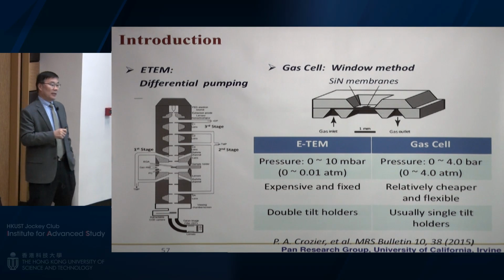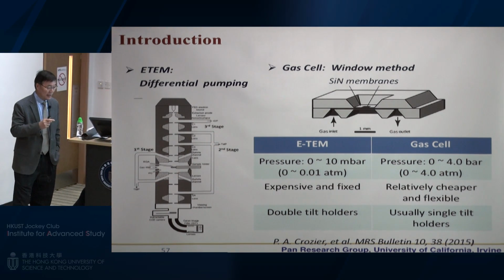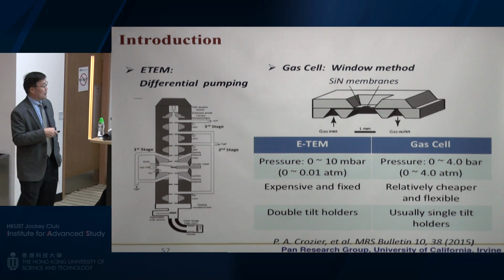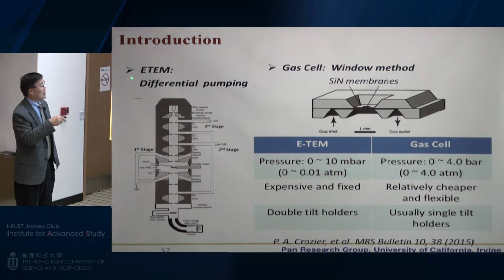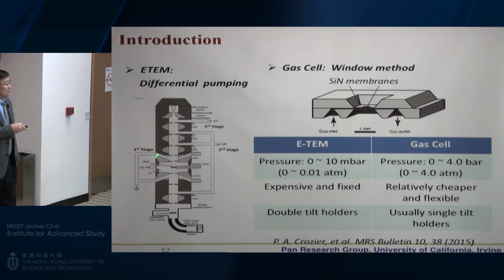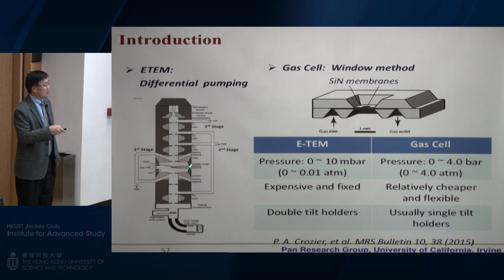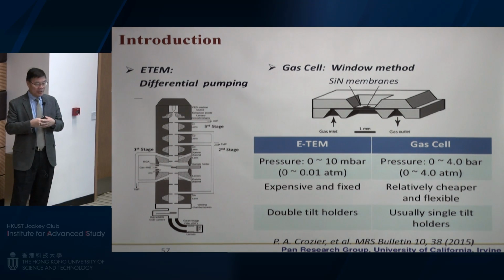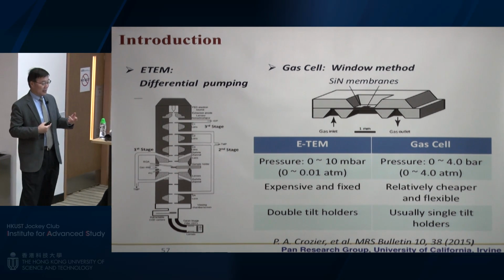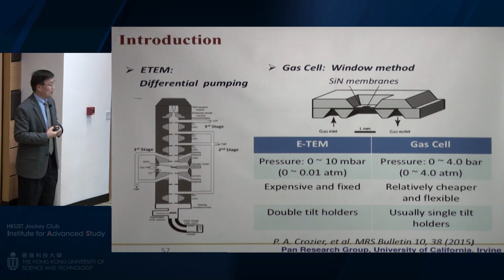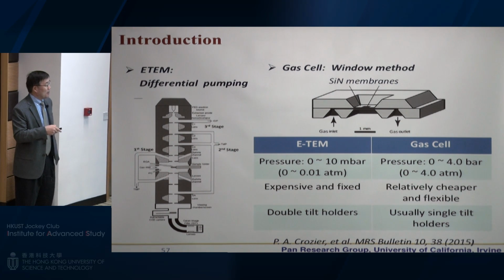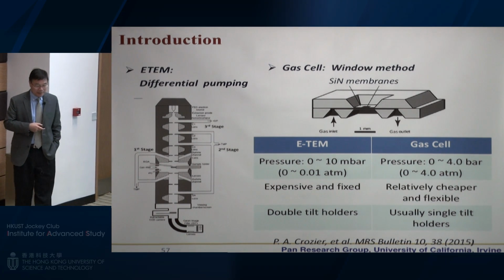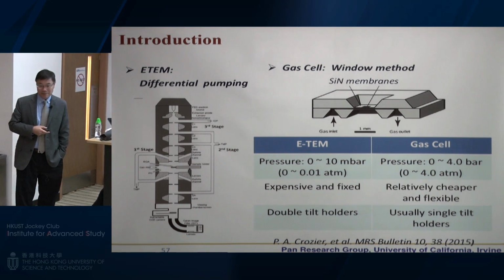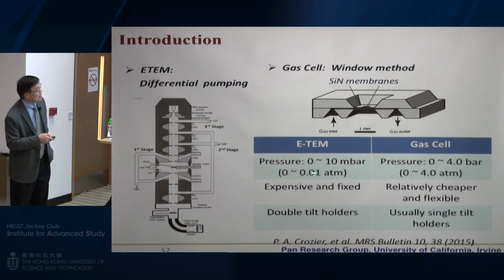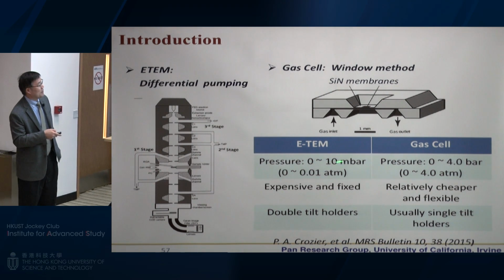Basically, you can do the high pressure in-situ experiment in TEM with two different ways. One is the so-called environmental TEM called ETEM. ETEM is from FEI company. They have built a special pole piece so that around the pole piece the pressure is differentially pumped, and then you have a high pressure in that area. Introduce a different kind of gas, and you can see visual microscopy and spectroscopy. But this pressure is still pretty high, and they could do probably 50 torr or 50 millitorr. ETEM is until about 10 millibar.